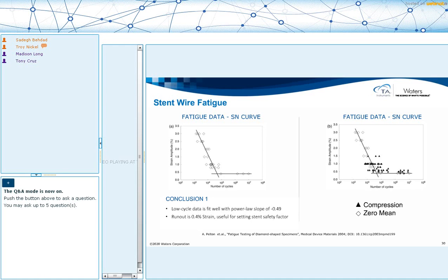And then on the right, you can see a second set of data that is shown over the first set. So the first set was sort of bidirectional testing. You had zero mean strain and you were oscillating around that up and down. In the second set, we are applying a mean strain, a compressive mean strain, and then we are repeating the same. What is interesting is that we see that the behavior is not significantly different, and the endurance limit does not change, although we are applying a mean strain over the oscillation strain.